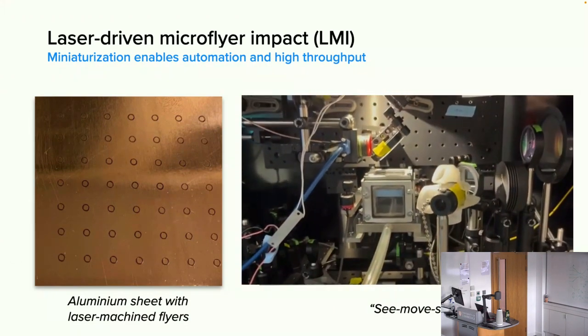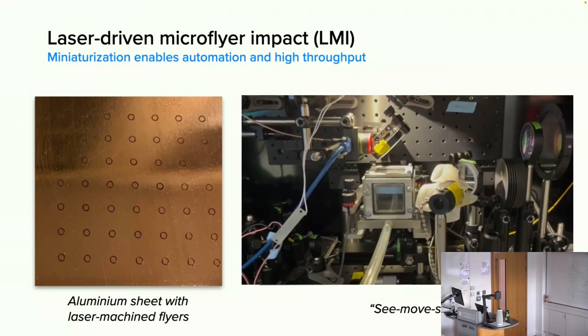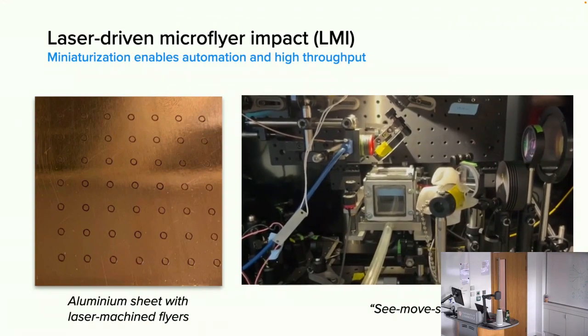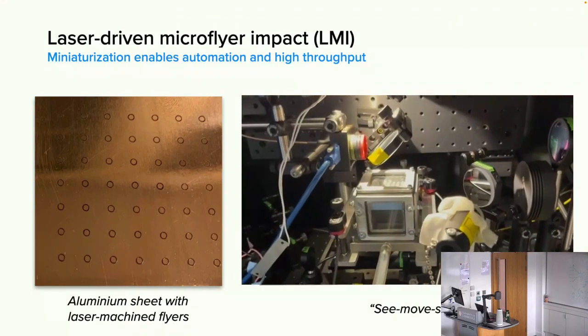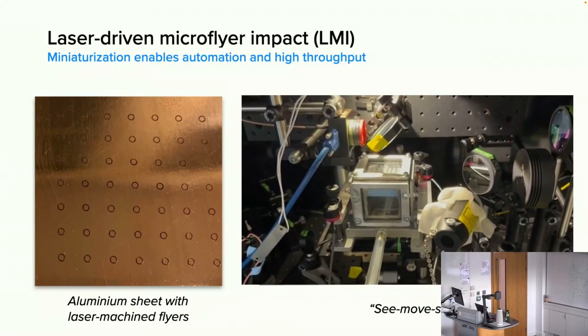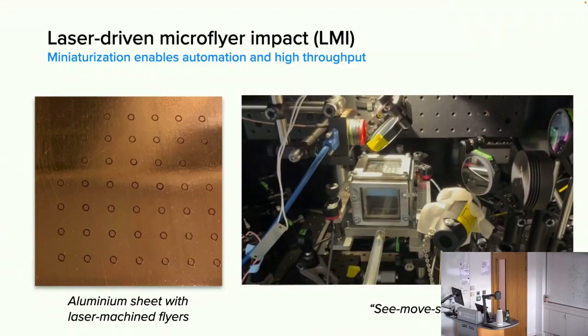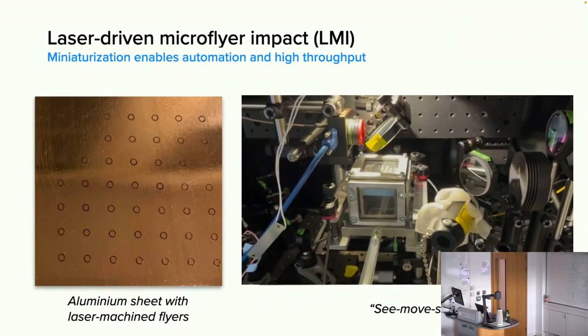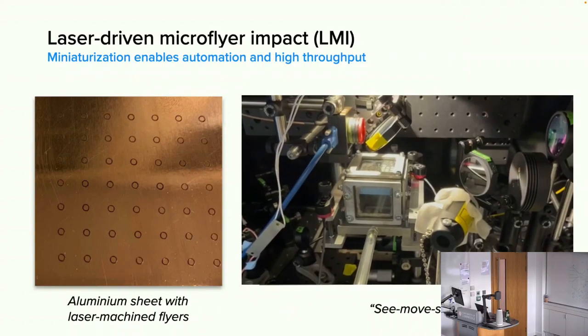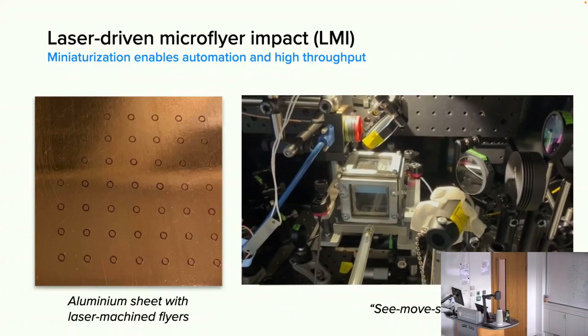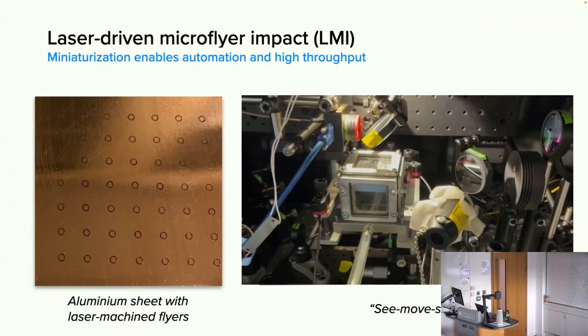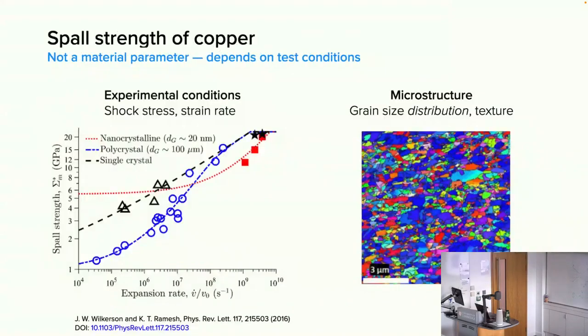So we've gone from being able to do 1 or 2 tests per day to doing a test every few seconds. So we increased the throughput of this experiment by several orders of magnitude, many orders of magnitude. If you look really carefully, you see a dot appear right there on the actual experimental apparatus. So miniaturizing this experiment allows us to automate and dramatically increase its throughput.